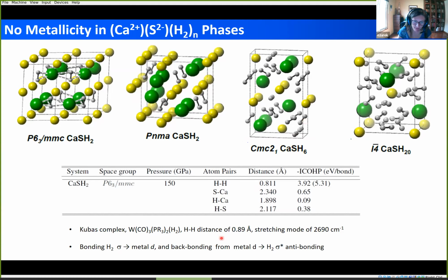However, we do see some very interesting chemistry going on here. For example, Kubas-like bonding between this H2 that interacts with calcium, where you have sigma to metal D transfer from the H2 and also back donation, and that's going to be modifying this H-H distance.